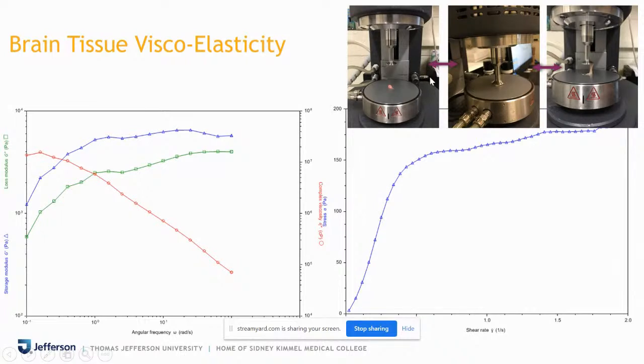The top panel that you see over here is the brain tissue of a mouse, and a geometry. You compress it, so you can see the brain tissue being crushed, and we ran two experiments with it. We did this frequency sweep experiment to see whether the viscoelastic behavior of the tissue matches a chemically cross-linked gel or a physically cross-linked gel. To our happiness, it was mostly towards the physically cross-linked gel system.